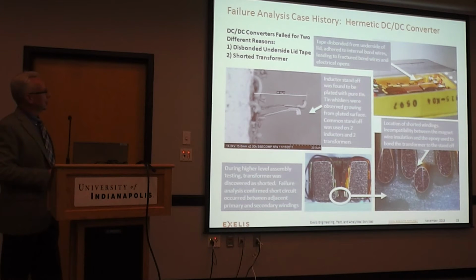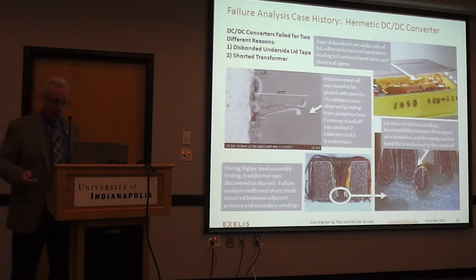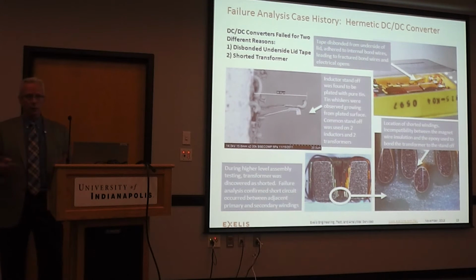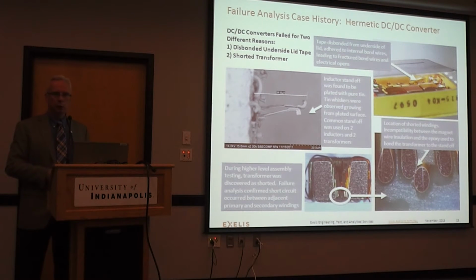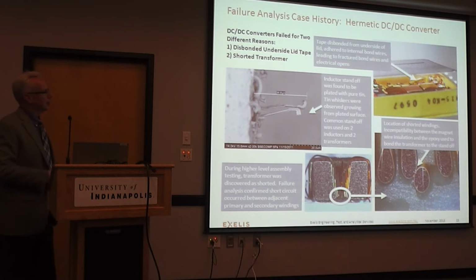We had a disbonded underside lid tape that drooped and adhered to internal bond wires. What are bond wires? Bond wires are little metal wires that make contact from one point of the circuit to another. So those of you who aren't in the electronics industry, just think of an uninsulated wire that goes from one place in the circuit to another, and there is a piece of adhesive tape that normally should stick to the underside of the lid. It can have multiple functions, including being a particle getter. So any incidental particles that are left inside of this thing during manufacture would rattle around and stick to that adhesive tape. Okay, but it disbonded, drooped down, and made contact with bond wires, and then they would pull up and cause an open.